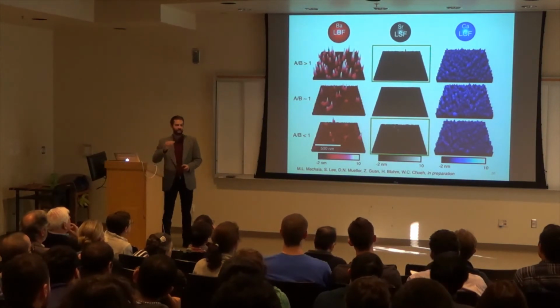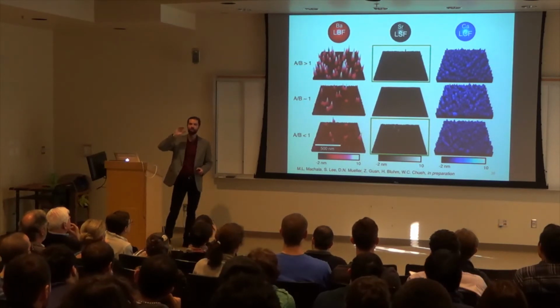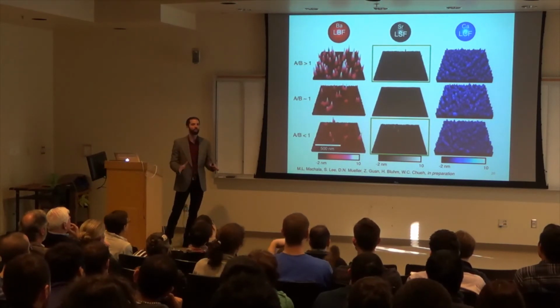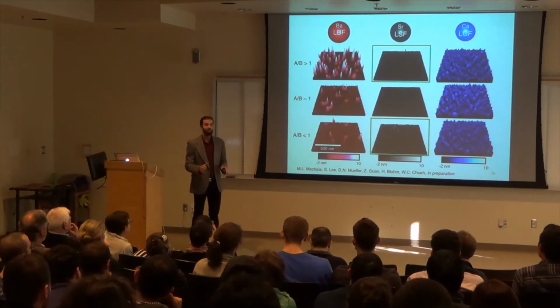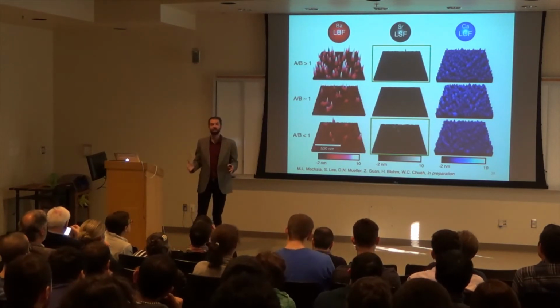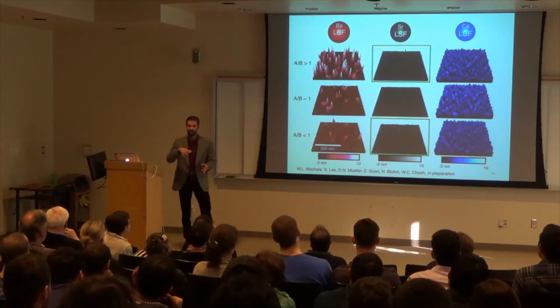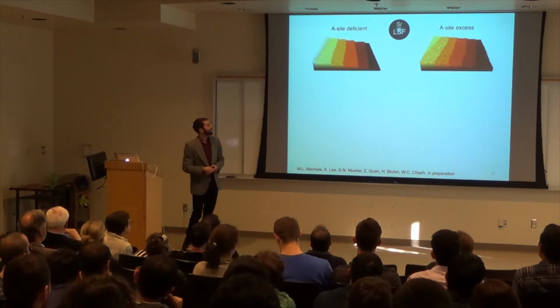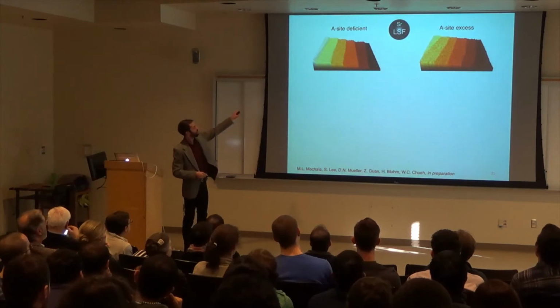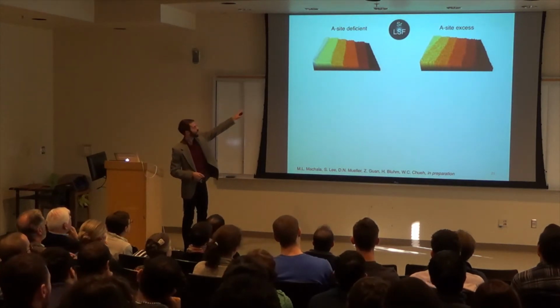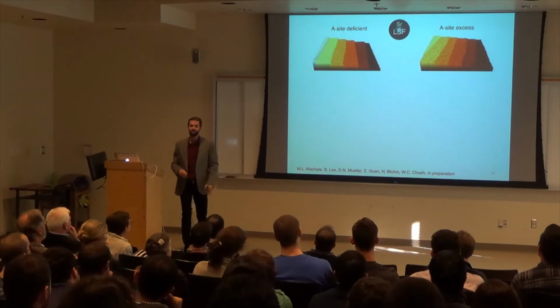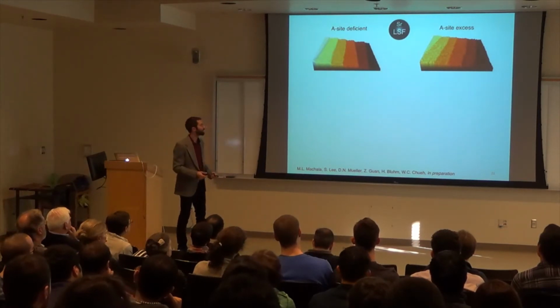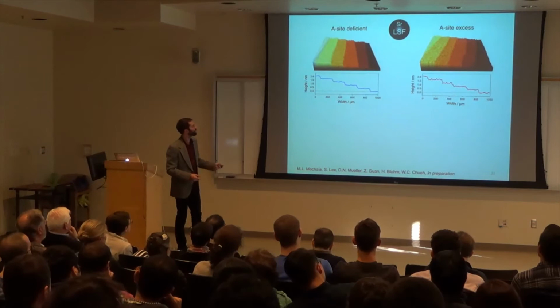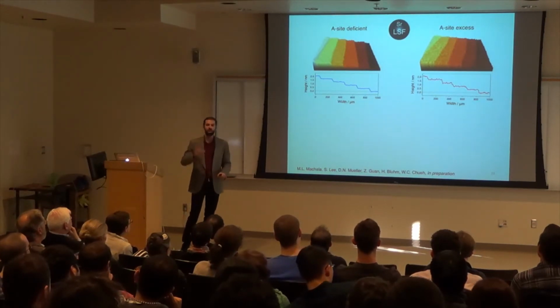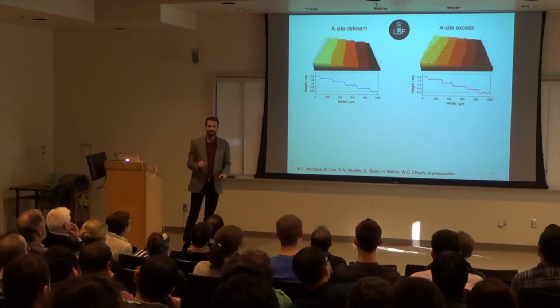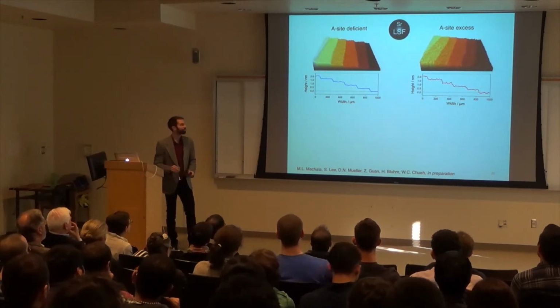Now, we're going to focus in and try to understand what's happening on the top atomic layers of the sample. To do that, we need a very well-defined model system. And what we do is we use atomically flat substrates to put our films on top of. This is what they look like. These are atomically flat lanthanum strontium iron oxide on top of strontium titanate, which is a single crystal perovskite as well. And they grow epitaxially. If you look at it from the side view, you can see each one of these steps is 1 unit cell in height. Just 1 unit cell. That's like 0.4 nanometers.